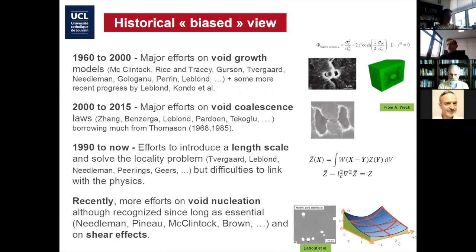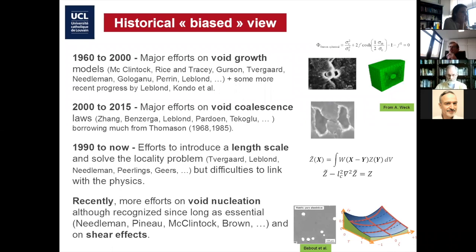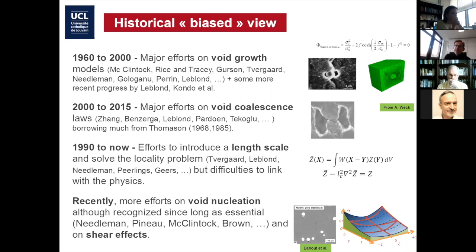Let me go through a very quick historical view on how the community has addressed this failure phenomenon from a micro-mechanical and microstructure viewpoint. It is not unfair to say that from the 60s to probably the year 2000, the focus of the community was on understanding the growth of voids — not focusing too much on how they nucleate, not too much on how they coalesce, but essentially the growth process. There has been a lot of effort from McClintock and Rice and Tracy in the late 60s, the famous Gurson model, to model the growth process and predict how the void radius and volume fraction evolve with plastic deformation for different loading conditions.